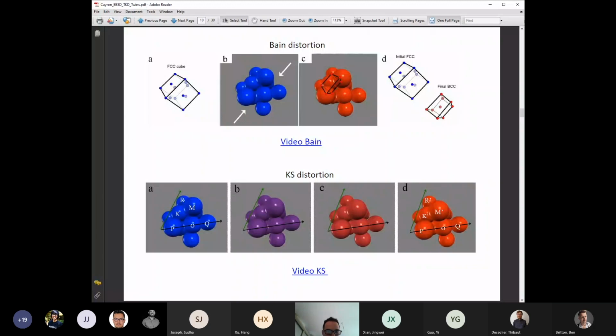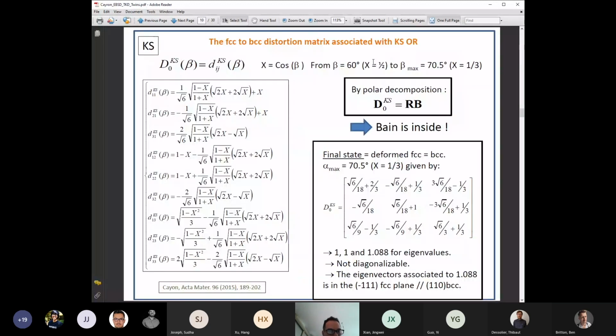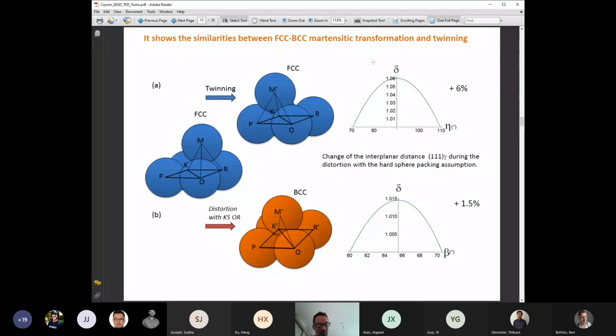Here is an example of the calculation to transform FCC, face-centered cubic, to BCC continuously, just with one parameter, which is an angle beta. Actually, you take the cosine of beta, that I call x, and you can go continuously from FCC to BCC. You can calculate the distortion matrix for that. I will skip the details, but it's just to tell that you can do calculation.